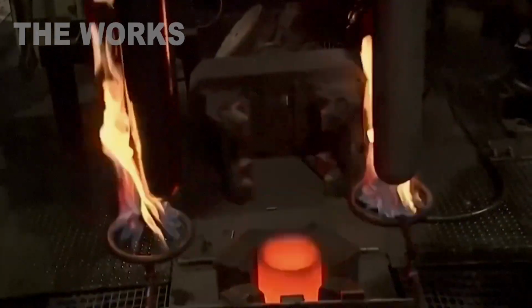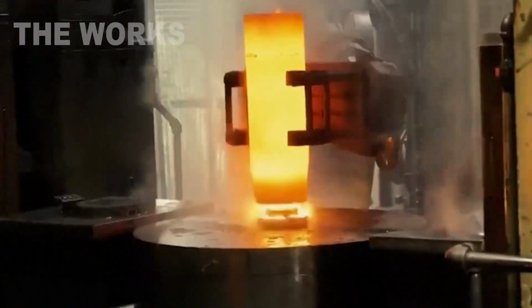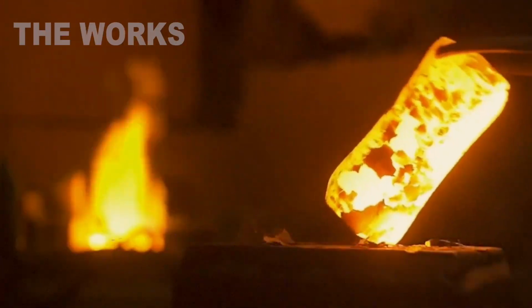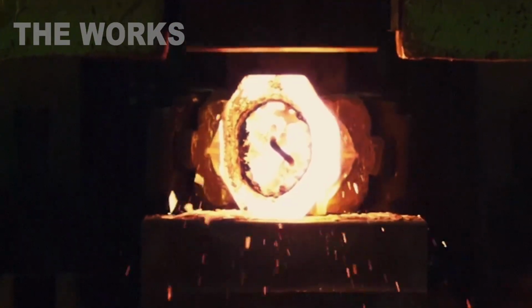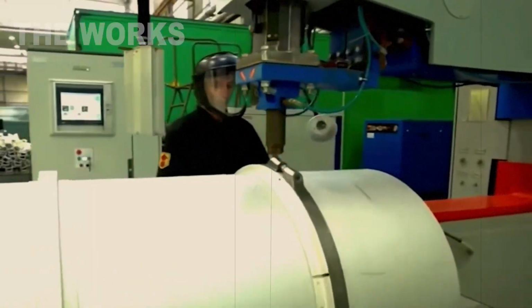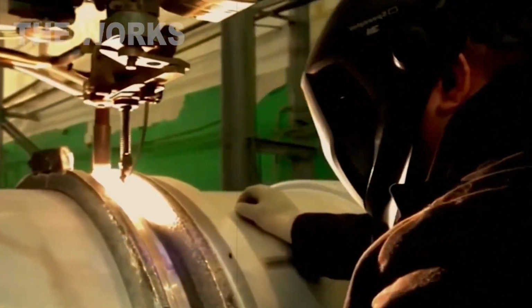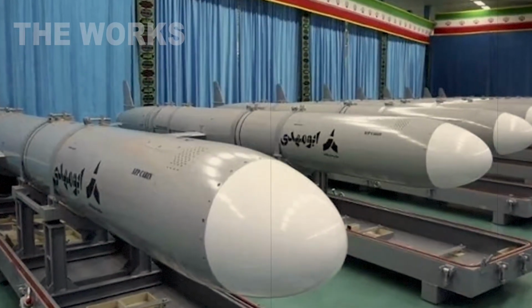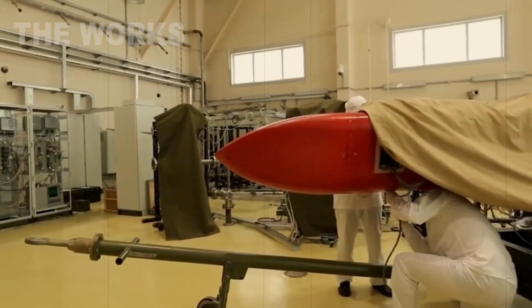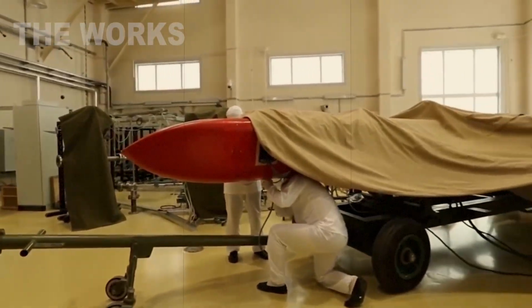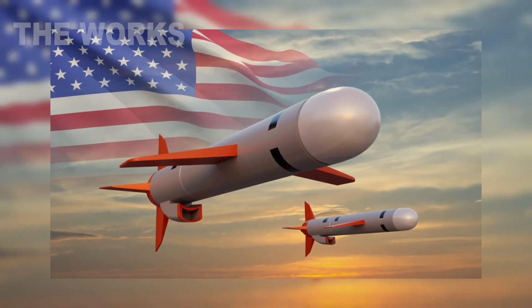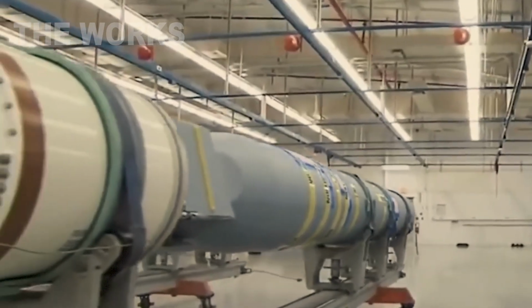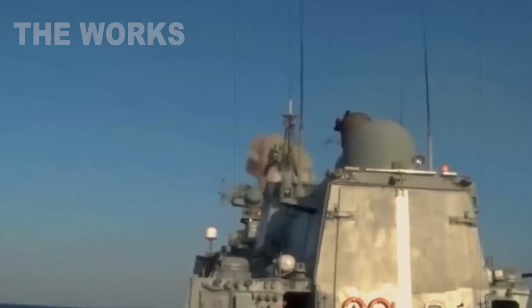Blanks are cut with laser or water jet installations with tolerances up to 1/100th of a millimeter. Then press forming. Large hydraulic machines bend metal like fabric. Welding is conducted in an inert atmosphere, often by robotic arms, to avoid even the smallest oxygen inclusions. Technologists check welds hourly with ultrasound and apply special anti-corrosion coatings. Even the inscription Tomahawk isn't applied as decoration, but as a marker of version and the missile's history.